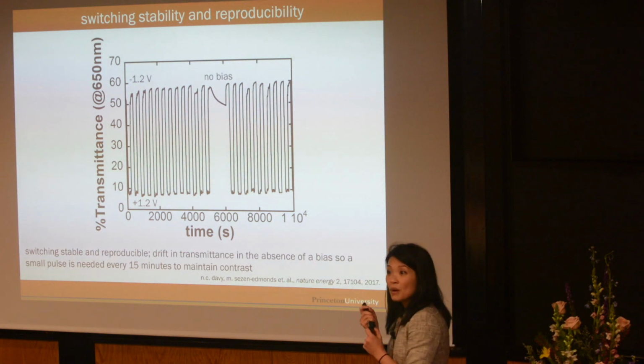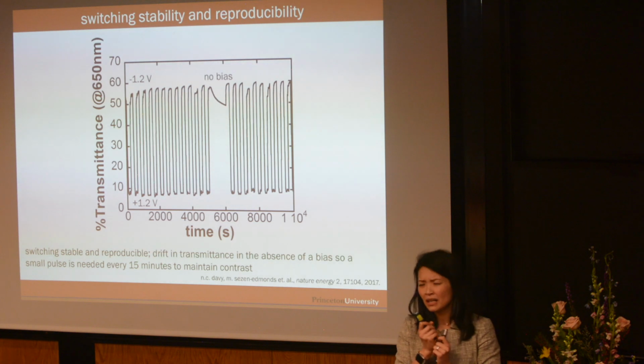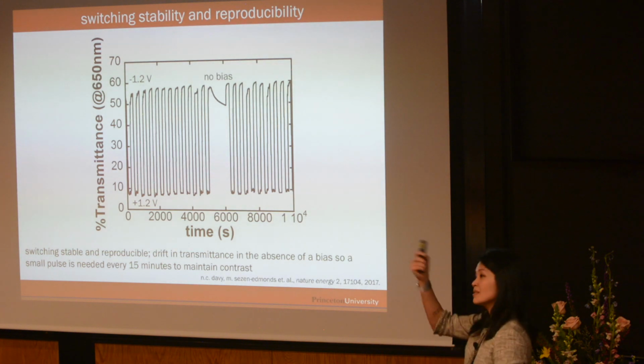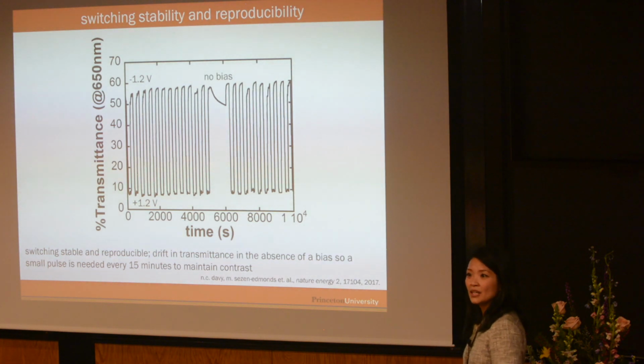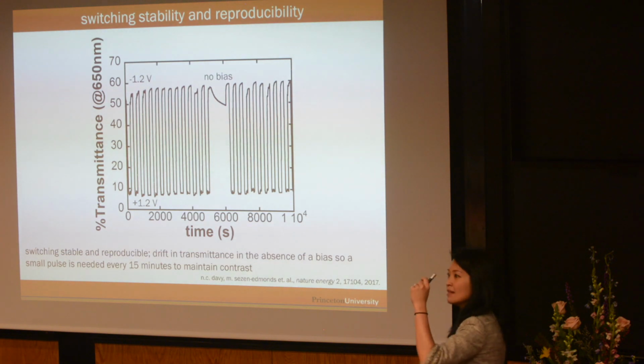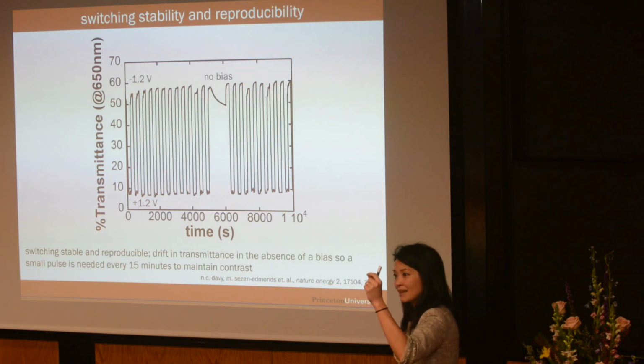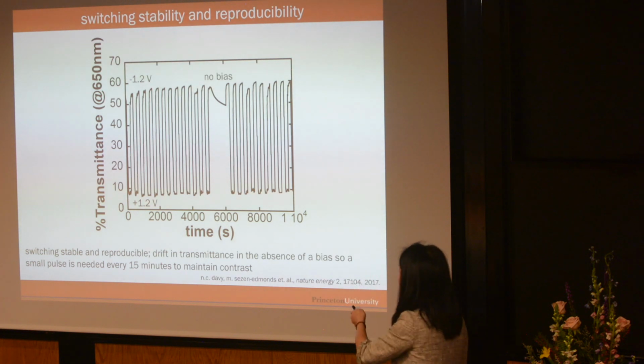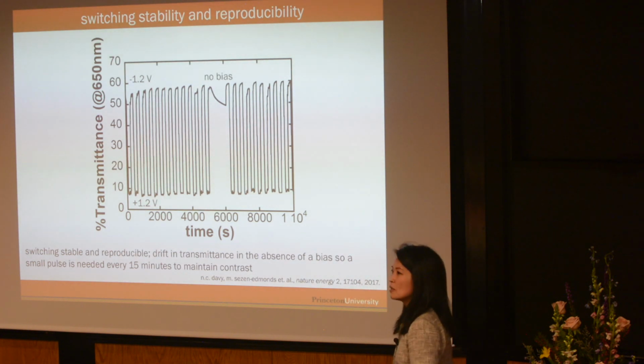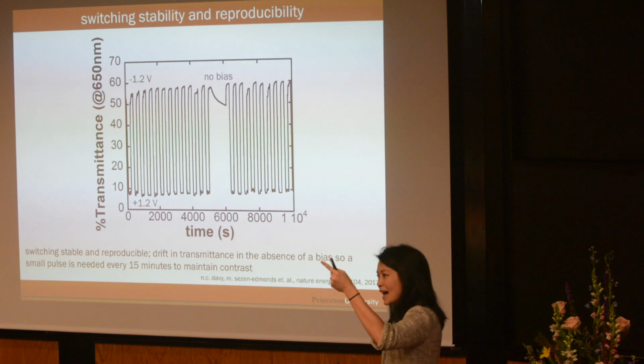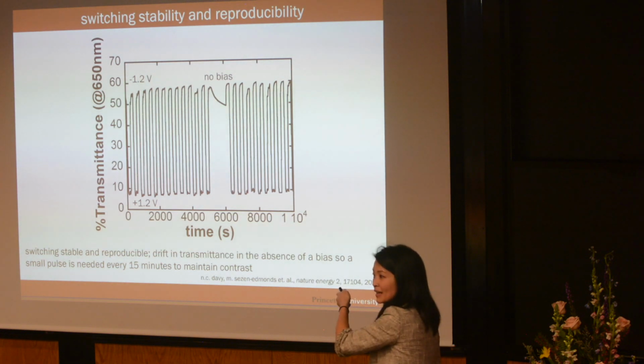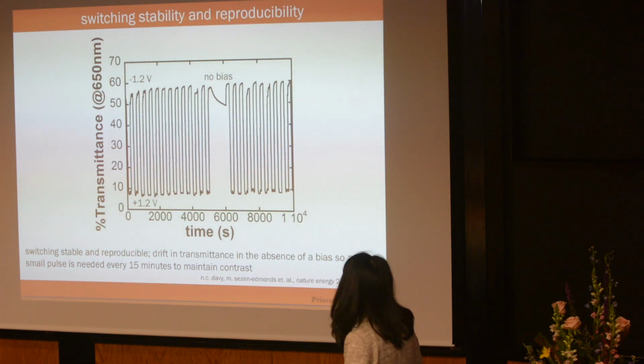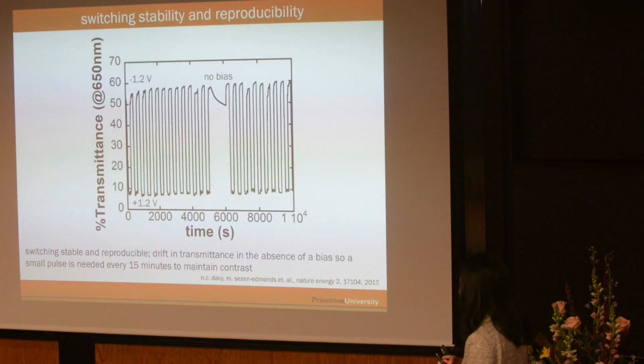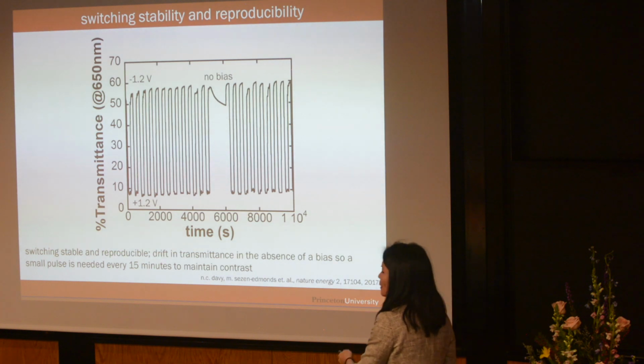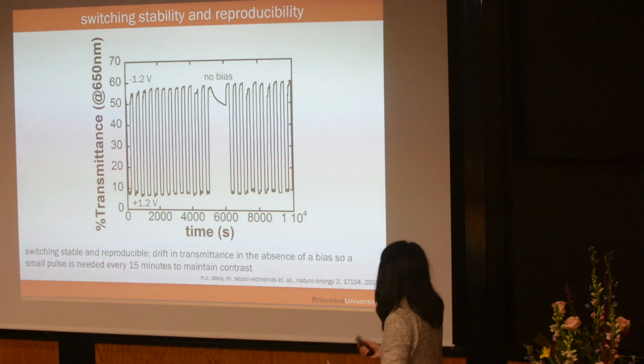It's nice. The one thing that's nice about electrochromic technology is that once you pulse it to the right oxidation state, you don't need to maintain that voltage in order for it to stay at that state, okay? But it's going to slowly decay. So what it means is occasionally you have to pulse it again to get it back to whatever state you want to get it back to. But you don't need a continuous supply of power in order to maintain it in its oxidation state. So this is to show the pulse. So we decided that we need to pulse it every 15 minutes to maintain contrast. So that's not a big deal.